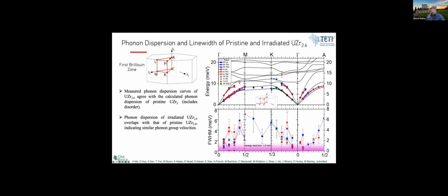We also have some first principles calculations of the phonon dispersion curves. These had to include some disorder and unfolding because the zirconium and uranium are in a random solution to begin with, and so you have to include that disorder, otherwise you get unstable phonons. But the energies agree pretty well, and the energies are not that strongly affected by the irradiation, but the lifetimes are in certain places. You see down here where the lifetimes are plotted, some of the lifetimes along the middle of the zone kind of jump up. But it's generally pretty complicated because some of them actually go the other way,